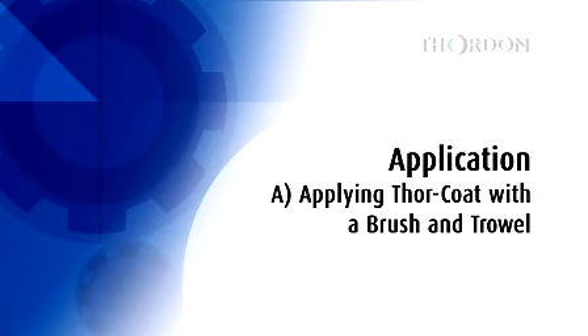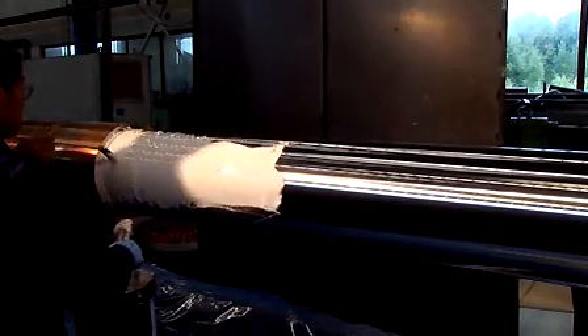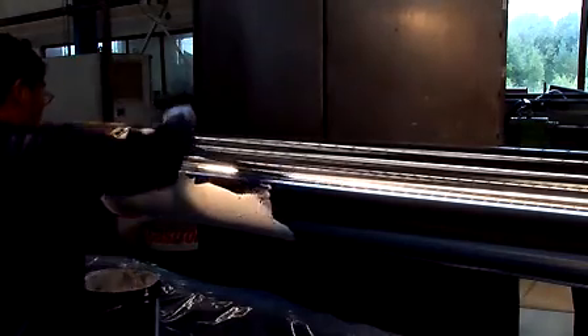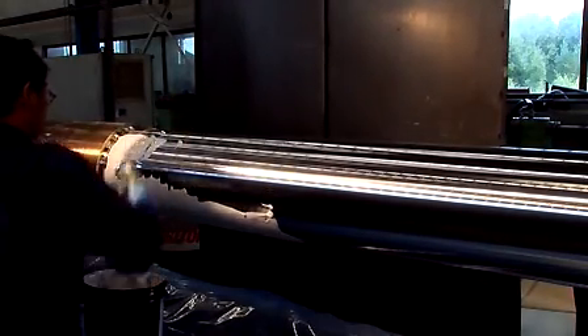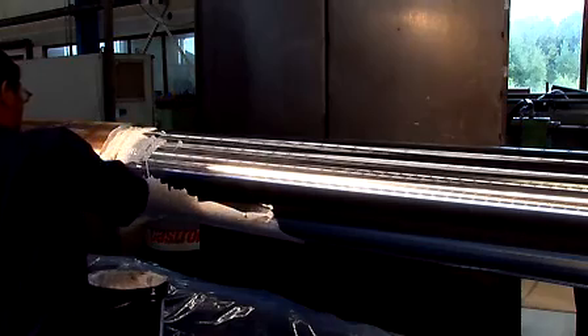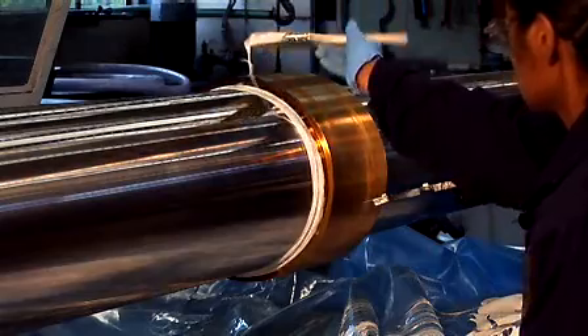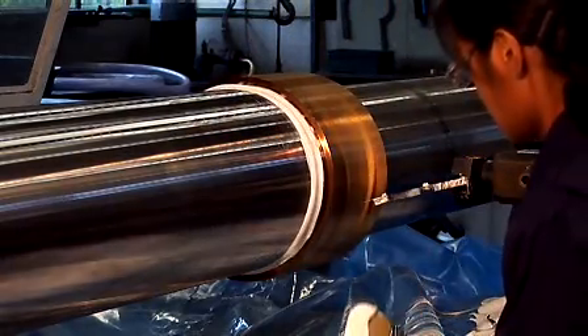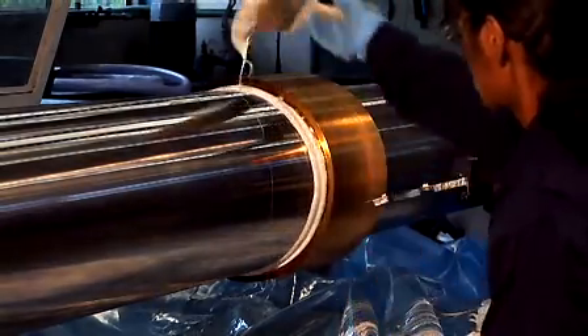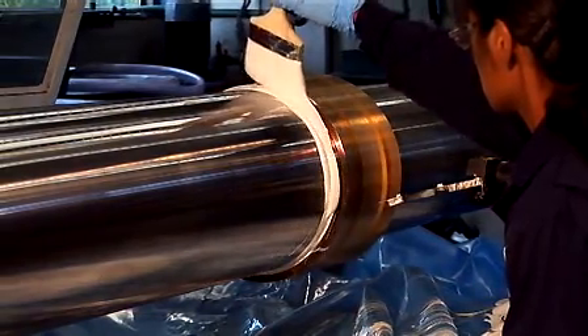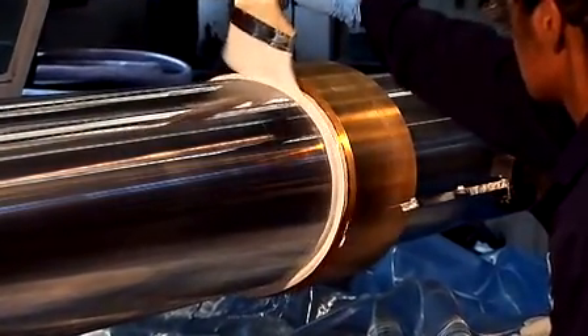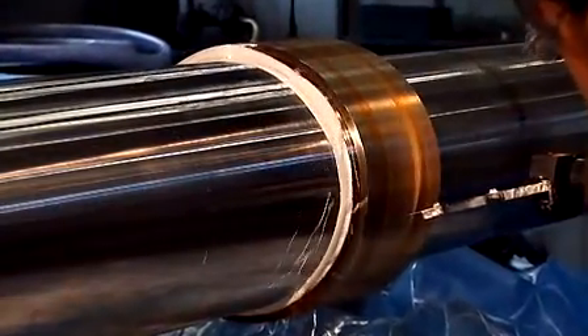Depending on manpower and materials, Thor Coat can be applied either with a brush and trowel or using a doctor blade mounted on a lathe. Regardless of which coating method is used, the transition to sleeve or liner requires special attention. The coating must provide a smooth profile in the transition area, extending Thor Coat beyond the grooves to the liner outside diameter. It may be necessary to apply 2 or more coats to this region. Using the brush supplied with the kit, apply Thor Coat to the top third of the shaft.